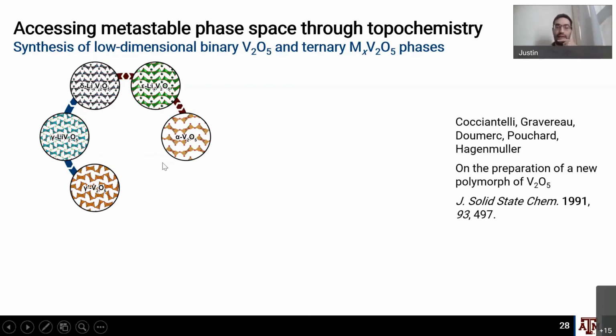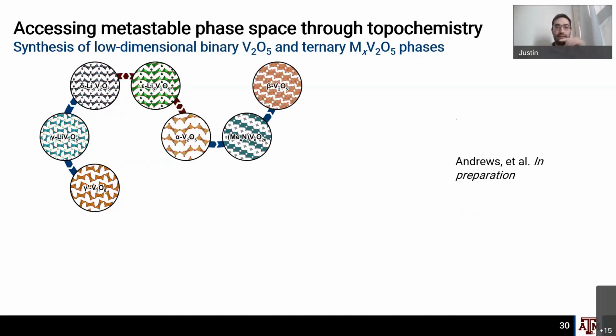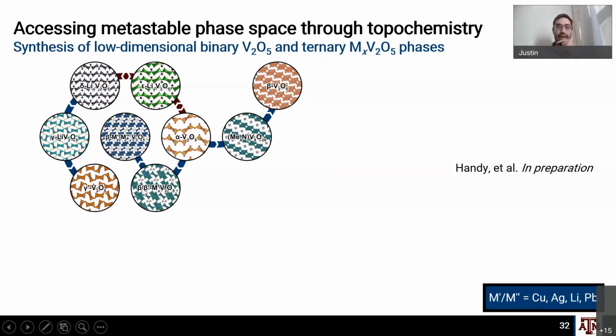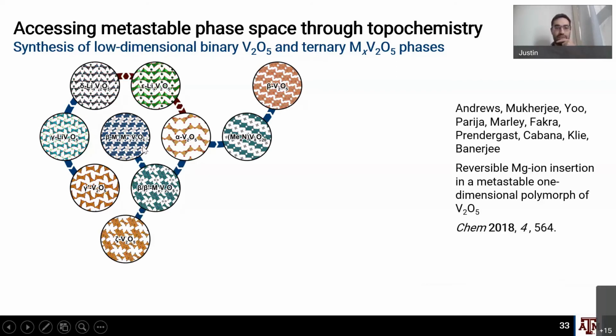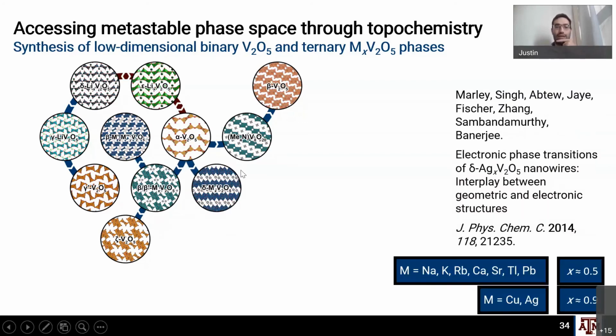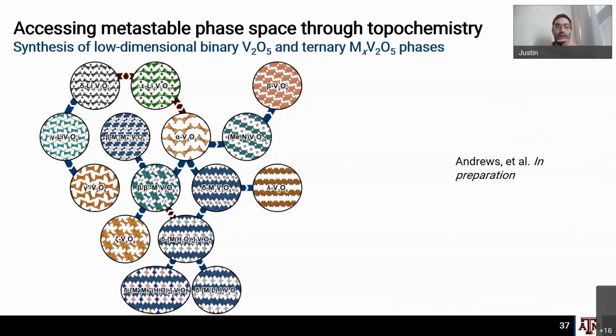And so what's interesting about this is it allows us to look at how structure and electronic structure in particular change the function and bonding. This is just one example of this. A lot of work we can also do is intercalate with certain organic cations to get different V2O5 sublattices, and then deintercalate those to make different polymorphs as well. We can intercalate with larger cations to make these one-dimensional tunnel structures, quaternary phases as well. Joseph Handy in the group has been working on this. And then if we deintercalate these larger ions from these structures, we can also get one-dimensional tunnel structures. We can intercalate hydrated ions within the layers to get double-layered V2O5 structures, and we can change the coordination sphere on those. And then we can also deintercalate these ions from the double-layered structures to get van der Waals bonded V2O5 structures that are metastable.